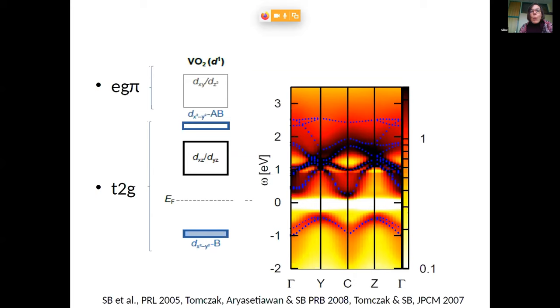And the reason why you can do this, actually, is that if you go to the bonding, antibonding basis of the A1G orbital here, you find that within the negative frequency range, the bonding self-energy is pretty much a constant. And in the positive frequency range, the antibonding self-energy is pretty much a constant. And if you take just these two constants as effective orbital-dependent potentials, you do the band structure calculation, you get this thing. So this tells us that if we have this dimer physics, we can nicely approximate the many-body dimer effects by this kind of potential.